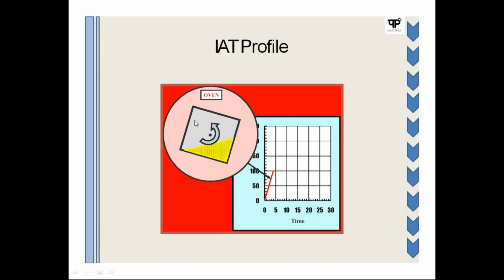Now this is a part you can see once you're adding this material, feeding this material and keeping this mold while rotating inside the oven. So this is a stage where the material is just in a powder form lying on the mold surface. Next, once it starts getting coated on the inner side, the surface of the mold, you can see this particular air temperature is going to change. This is the one you can see, the way it is coated completely.